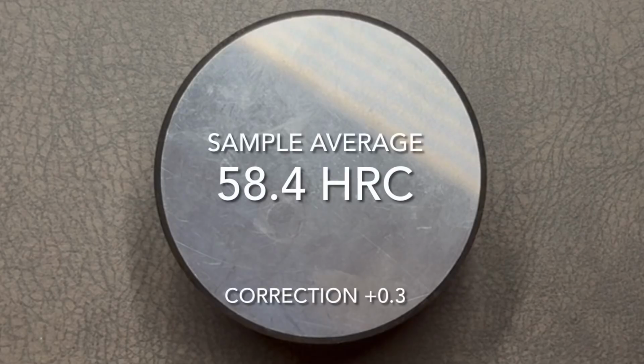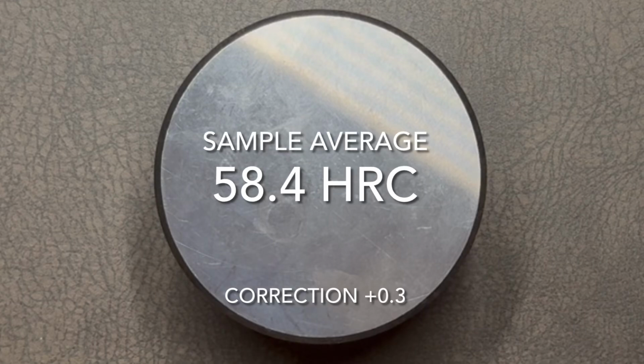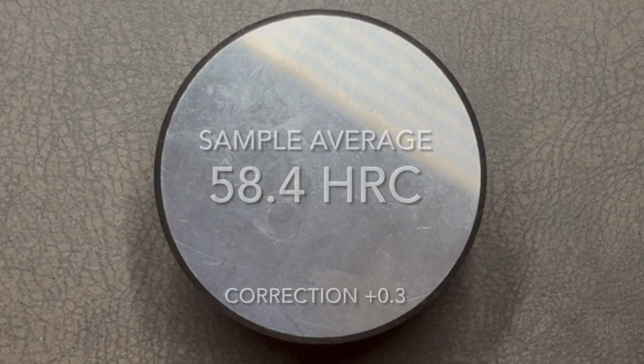So as you could see, during the calibration that I did 3 times, so 15 strikes altogether, the averages varied somewhat. So I took the average of all 3 tests and found the error. And the error was negative 0.3 points. So going forward, I will add these 0.3 points to the final value that the steel on the blade will show. So here is what I got in summary: 58.4, so my shift is plus 0.3. So let's see how that goes.